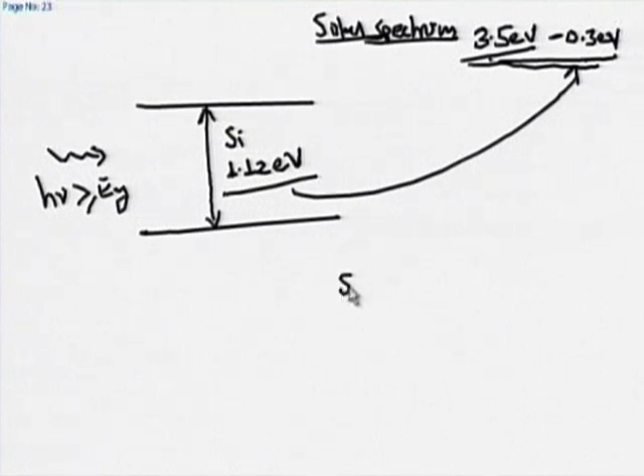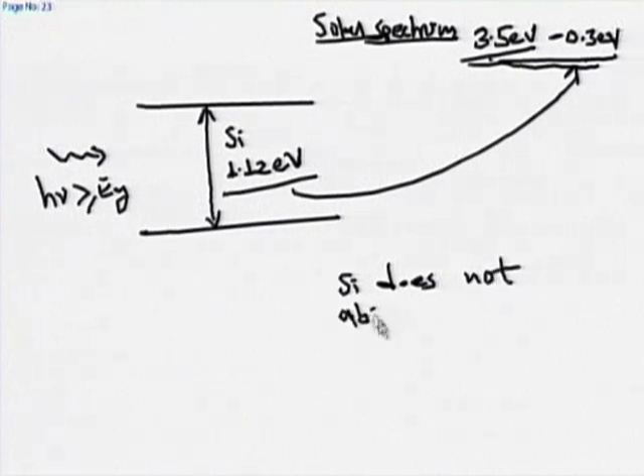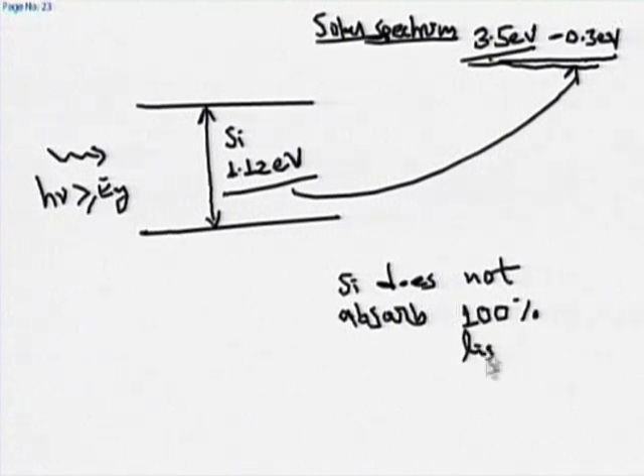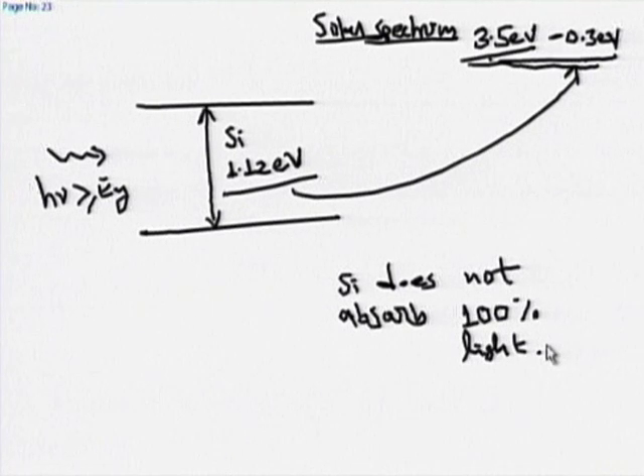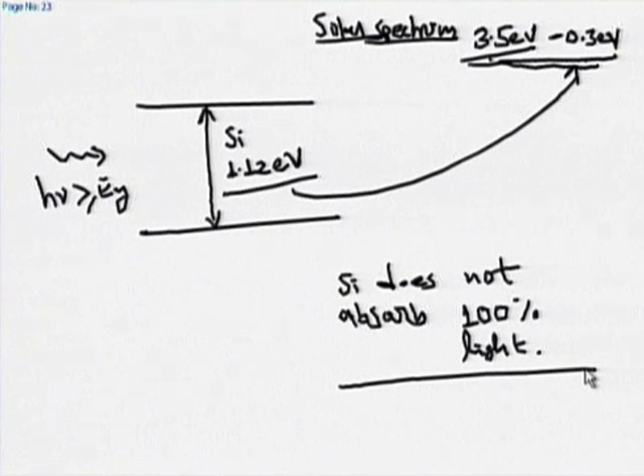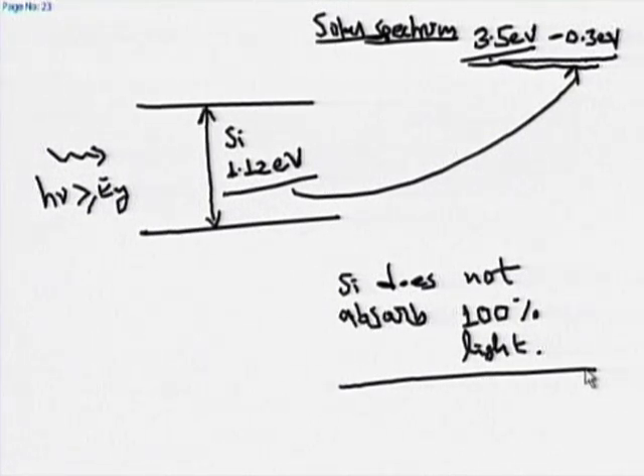Silicon does not absorb 100 percent of light. If it does not absorb 100 percent, its efficiency definitely has to be lower. That is one reason why solar cells have lower efficiency — no material, because it has a band gap, can absorb all photons. All photons with energy lower than the band gap cannot get absorbed, and therefore that material becomes transparent to some portion of the spectrum.